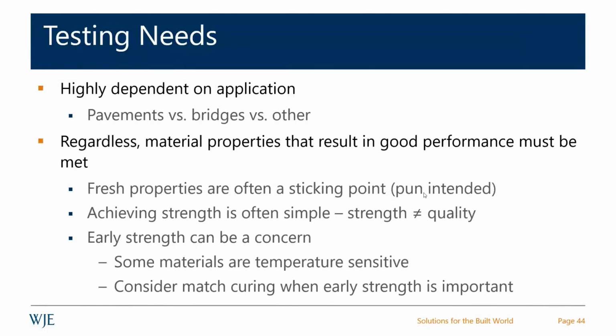We need to be assured that we get the strength that the structural design needs. But too much strength does us no good, really. And we've made this association that higher strength means higher quality, and it actually can lead to poor durability. And then early strength is really the one where some of these materials are very sensitive to changing temperatures. So maybe have a summer mix and a winter mix, for example.